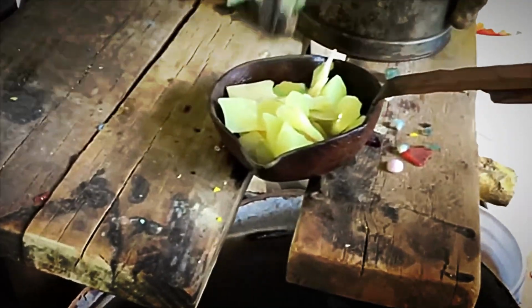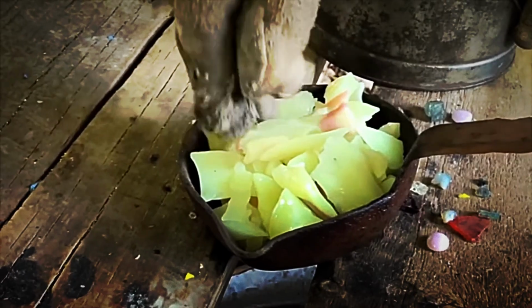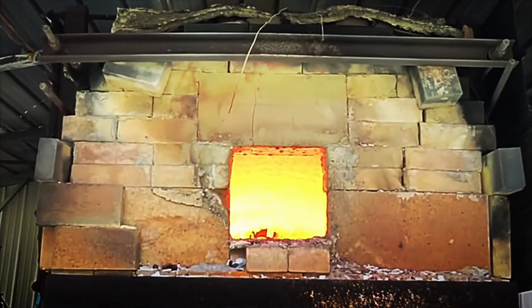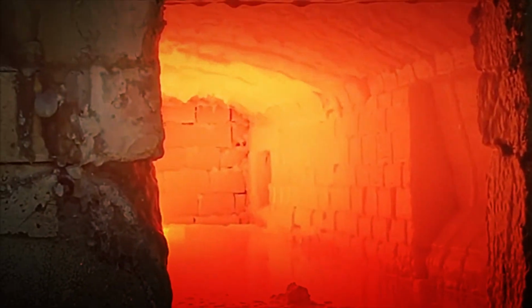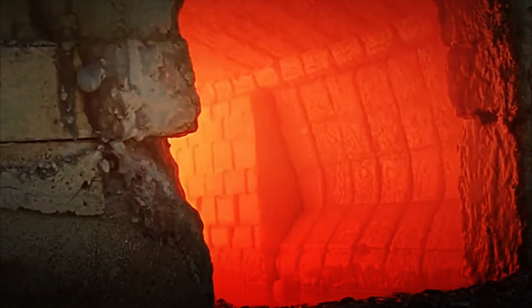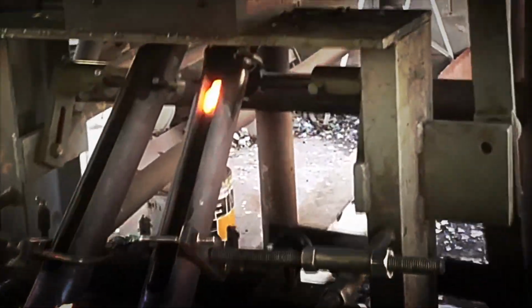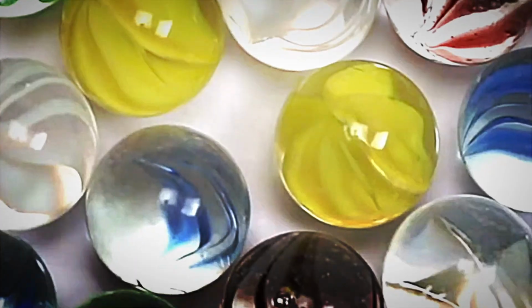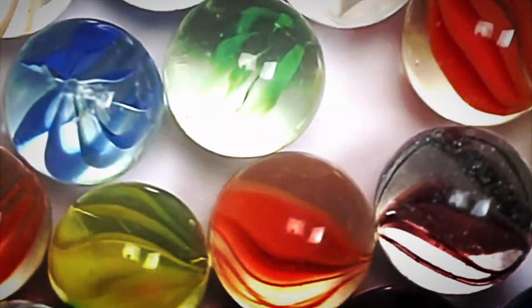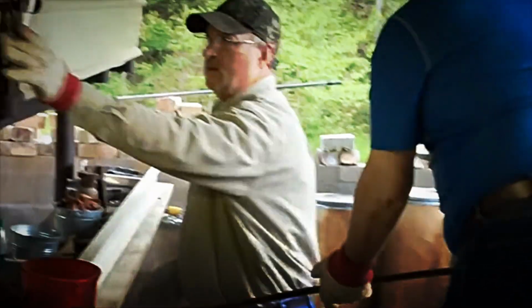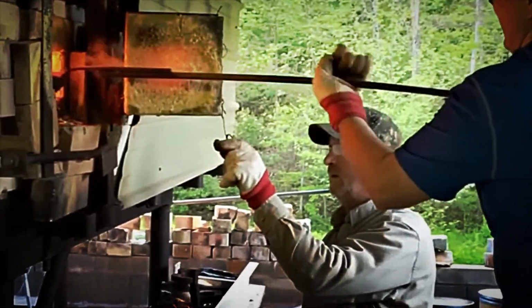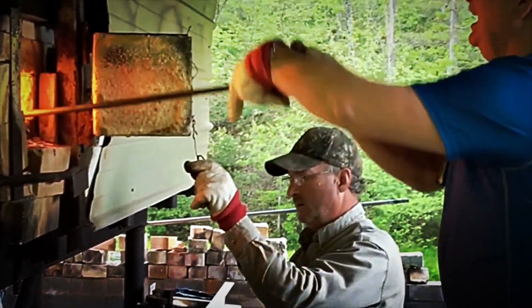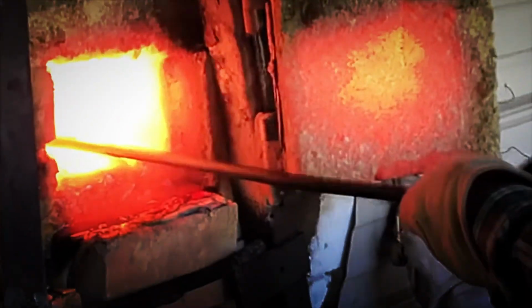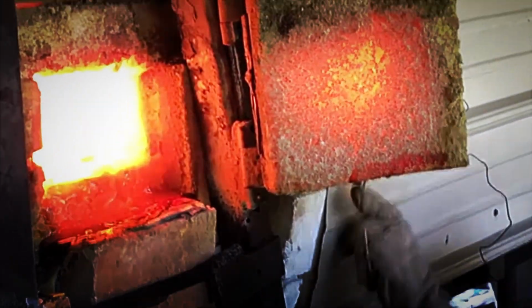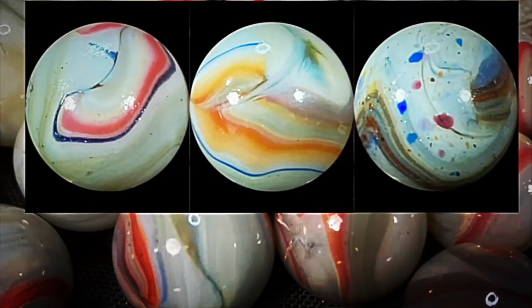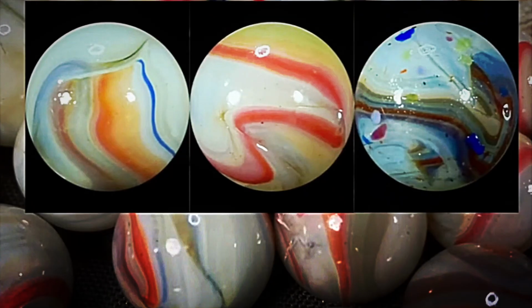The coloring is achieved through specific metal oxides added directly to the furnace or in areas near the exit of the molten glass. These compounds do not fully mix, but instead form internal color currents that become trapped inside the marble. This phase requires extremely precise control. The amount of dye, the moment of incorporation, and the exact location all directly affect the final result. Small variations can generate notable changes in the tones, intensity, or shape of the patterns, so the process is constantly monitored to maintain consistency in each batch.